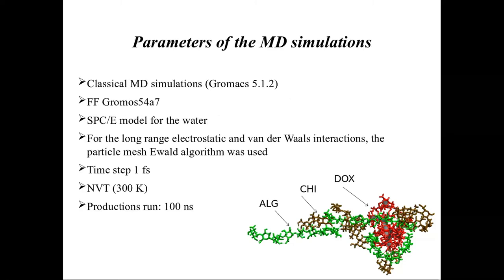To achieve our goal, we performed classical molecular dynamics simulations with a GROMOS-type force field — specifically version 54A7, which is parameterized to better represent the pyranose conformations of sugars and also uses quantum chemical calculations to better represent the polar functional groups attached to the polymer chain. For long-range electrostatics and van der Waals interactions, we applied the particle mesh Ewald algorithm, with a timestep of 1 fs and production runs of 100 nanoseconds.